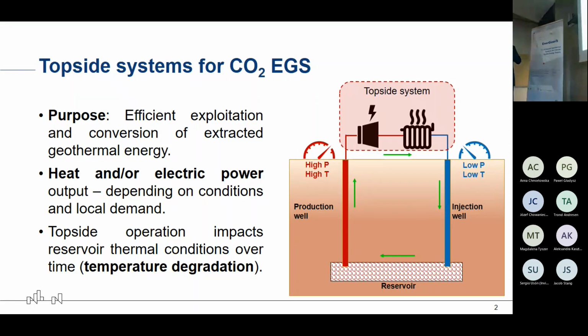So going to the presentation, I will just quickly say a few words about what the topside system of the CO2 EGS is. We're basically talking about a turbine and a cooler that allows us to utilize the high pressure and high temperature coming from the production well and then put it back with a lower pressure and lower temperature. The purpose of this whole topside system is the efficient exploitation and conversion of extracted geothermal energy. So the hot dry rocks that give the heat to the working fluid, which in our case is supercritical carbon dioxide, is the key point here to utilize it in the most effective manner.